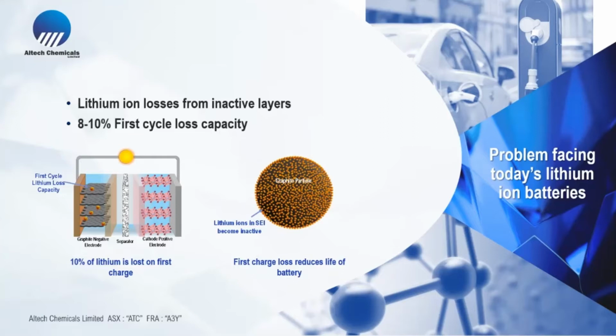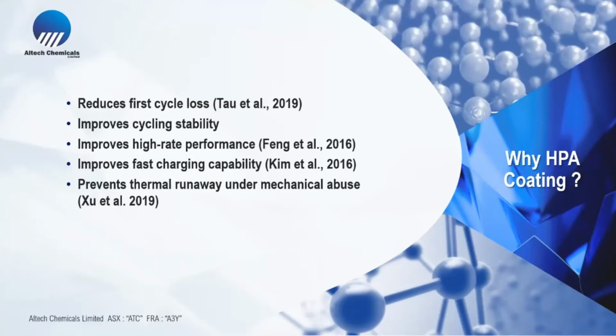And essentially what it does, it forms an SEI layer around the graphite particles and it becomes inactive to the battery. So this is a major problem facing the lithium battery industry. And what happens during the life of the battery is that the SEI layer cracks, it exposes new sites and more lithium is absorbed. And also hydrofluoric ions in the electrolyte break the SEI layer, expose new sites, and then more lithium is absorbed. So there's a continual consumption of lithium during the operation of the battery. And there's a lot of research that shows that high purity alumina coating around the graphite particles resolves this first cycle loss problem. It improves the life of the battery, fast charging capability, and also the safety of the battery or thermal runaway.